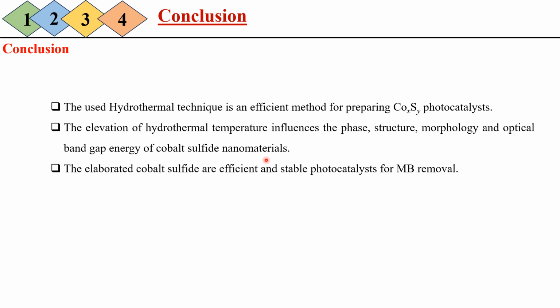To conclude this work, the hydrothermal technique used is an efficient method for preparing cobalt sulfide photocatalysts. The elevation of temperature influences the phase structure, morphology, and optical band gap energy of our cobalt sulfide nanomaterials. And finally, the elaborated cobalt sulfides are efficient and stable photocatalysts for MB, or methylene blue, removal.